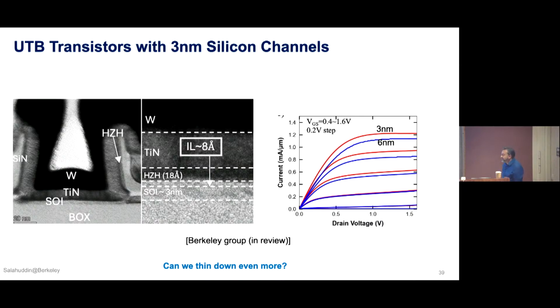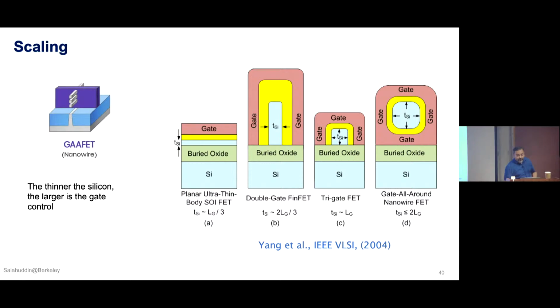Okay, and this now shows that even in 3 nanometer silicon, where we actually see very strong quantum confinement effects, the velocity is going up. So this allows us to work on the transport part of our scaling curve. Going down to thin silicon has other advantages. If you go down to thin silicon, you can also scale down the device. You can reduce the channel length of the device.